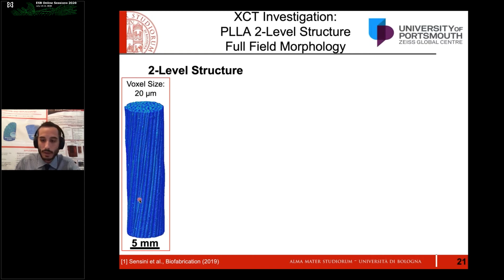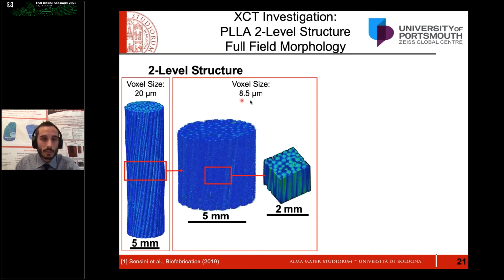Zooming inside with the voxel size, you can also see the electrospun nanofibers on the electrospun membrane, which is homogeneous, while in the internal bundles you can see that they maintain their axial alignment and porosity, suitable to better help the cells infiltrate inside.